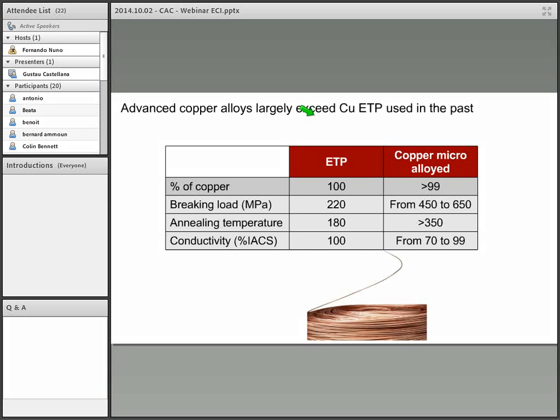That's really important because later you will see how important it is to have this high temperature in order to transmit more power. And it's really interesting because the conductivity is of course affected, but not too much compared with the solution on the market, the ACSR solution, which has a conductivity around 55% IACS. So these copper microalloys give interesting mechanical and temperature properties without losing too much conductivity.